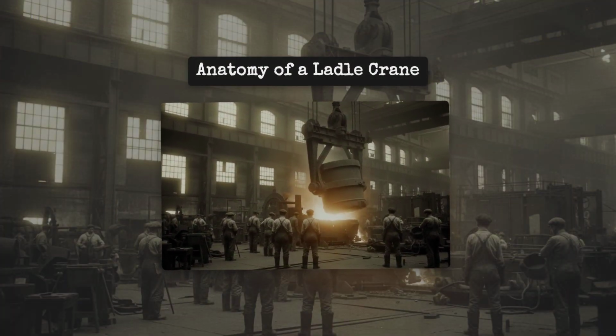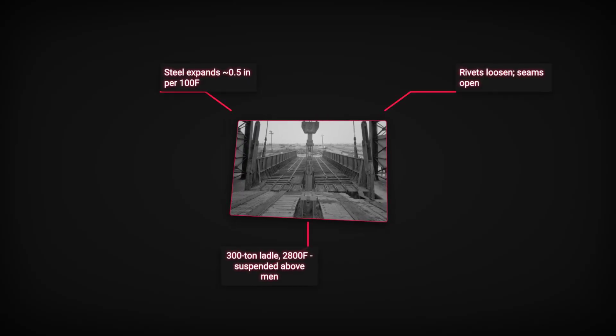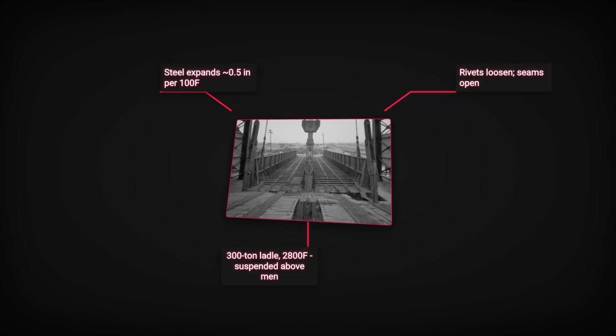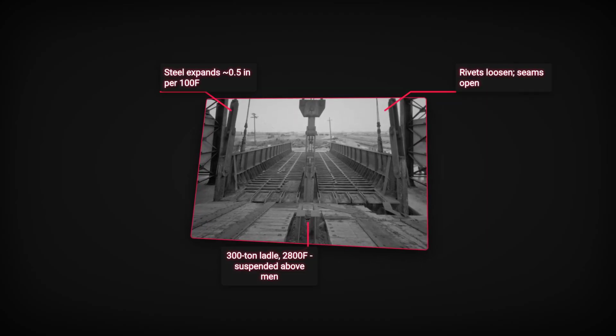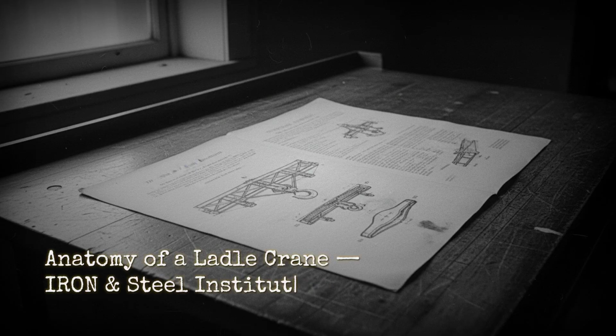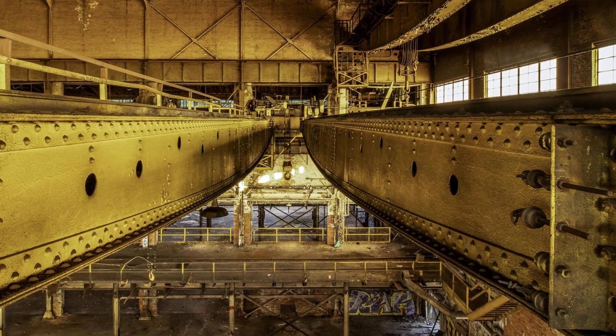Every inch of the crane exposed to the ladle's radiant energy is slowly softened, annealed by cycles of expansion and contraction. Steel expands nearly half an inch per 100 degrees. A boom might grow and shrink by several inches in a single shift, loosening rivets and opening seams. The Iron and Steel Institute's 1905 supplement notes that, after a year, main bridge members could sag by an inch from thermal cycling alone. Material choices were dictated by cost and availability.